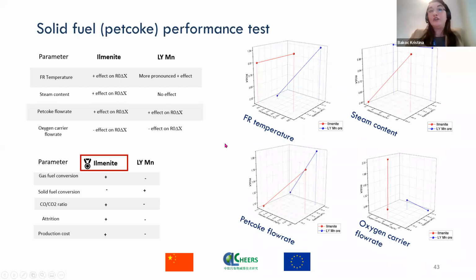However, additional solid fuel performance tests were performed, and the reason for this was twofold. On the one hand, we wanted to also test for the values of petcoke conversion and oxygen transfer capacities, but also we wanted to find the best indicators for the operation, which would help for operating the actual demonstration unit at the large scale. So what we found was that the fuel reactor temperature has, of course, a positive effect on oxygen transfer capacities, which is more pronounced in the case of LYMN than it is for ilmenite. In any case, the trend is the same for both of these materials for the same parameter.